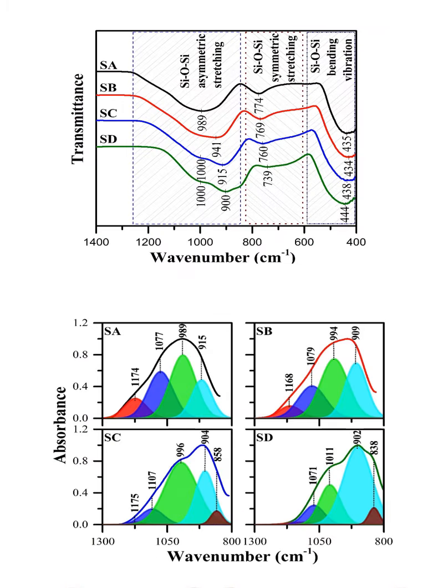In the FTIR, with the increase of the calcium oxide concentration in the glass, the breaking of the bridging oxygen bonds is promoted, generating a greater amount of non-bridging oxygen and increasing the depolymerization of the vitreous network. This can be seen in the deconvolution of the FTIR spectrum, where in the samples SA and SB a decrease is observed in the red signal of bridging oxygen, and in the samples SC and SD the red signal disappears and the brown signal appears. Therefore, the addition of calcium oxide in the vitreous network can generate depolymerization.